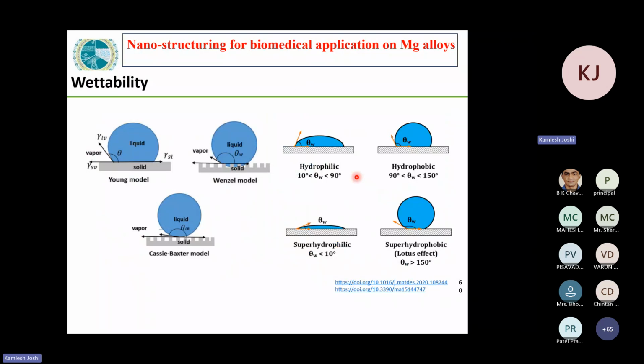After that, we tested them on the optical tensiometer for the contact angle measurement. In general we have Young's model, where contact happens between a solid and a liquid surface, and the energy is used to find the nature of the contact. If we create surfaces like this, it can have a Wenzel type of model, where the liquid penetrates inside the material, or it can have the Cassie-Baxter type of model, where it does not penetrate. So air pockets get inside the hollow surface, and the liquid droplets lie over the surface.